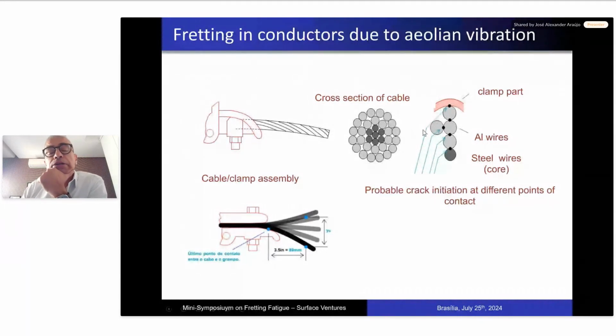Looking now at the top right of my slide, you will see that you can have contact between the aluminum wire and the clamp upper part, but also you can have contact between the wires themselves, right? In the vertical direction and in the horizontal direction, okay? Also, if this conductor is an aluminum conductor steel reinforced, you may have contact of the aluminum wire with the steel wire, and all these black points here are points that can develop fretting fatigue cracks, okay? So that's the way the fretting fatigue problem takes place in the connection between conductors and clamps.